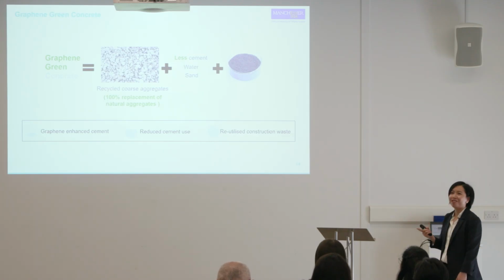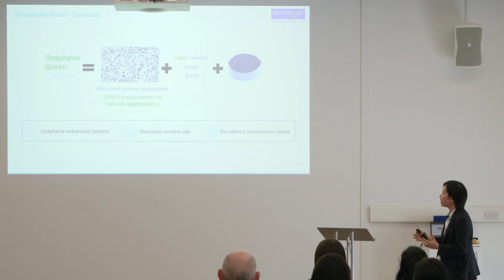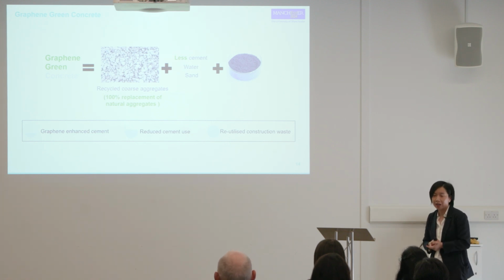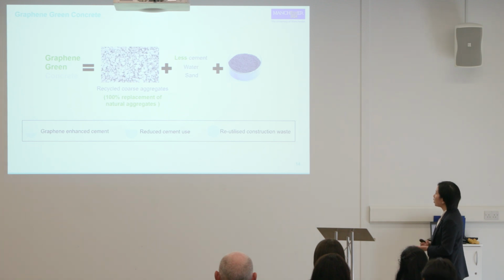So what is graphene green concrete? It is kind of concrete that uses a tiny amount of graphene and use 100% recycled aggregates to replace the natural aggregates, but still achieving comparable performance to the conventional concrete using natural aggregates, at the same time without disturbing the existing manufacturing process. And the technical uniqueness of the graphene green concrete include we use graphene to enhance the performance of cementitious material. We try to use less cement in the concrete mixture, and we use 100% the concrete waste as the coarse aggregate in the mixture.